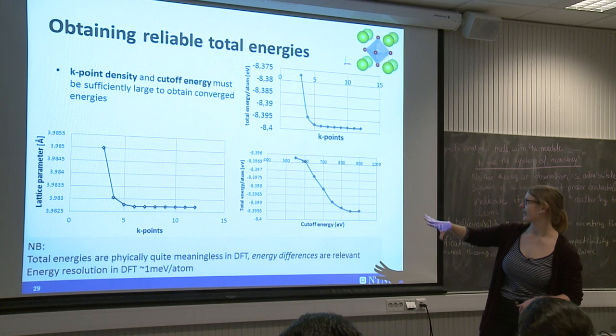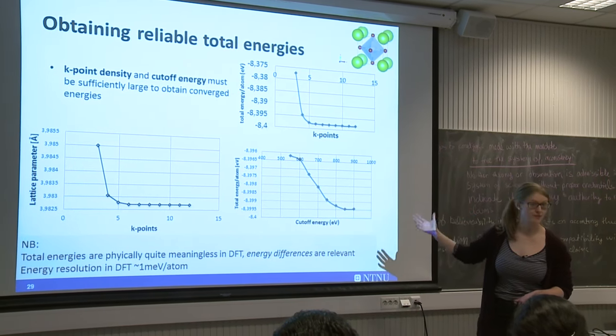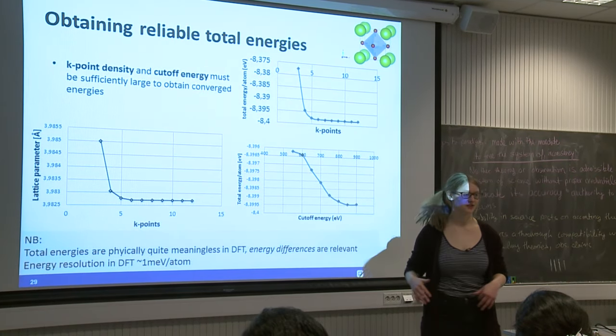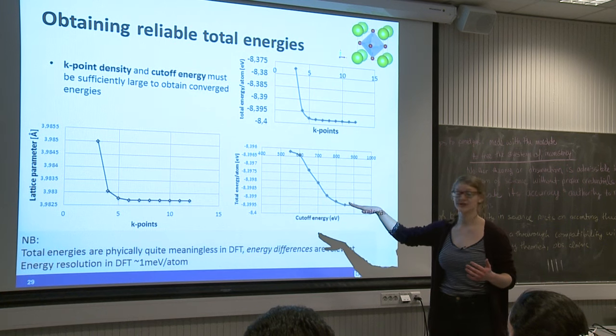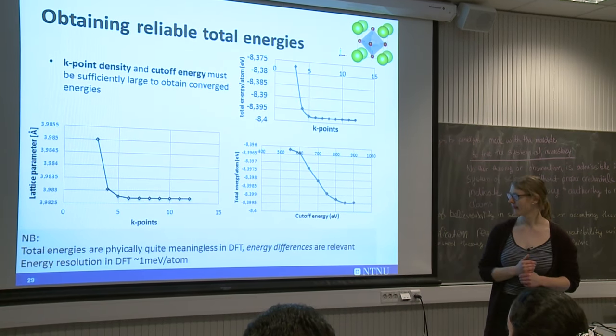And also be aware that the cutoff energy and the K-points also influence structural parameters like the lattice parameters, which we also see converge. Here it is plotted against the K-points.